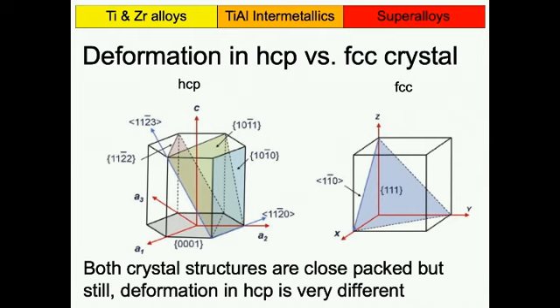This is a relatively close packed plane, but the basal plane as well. So both of those planes can act as a slip plane. And then on top of that, you even have one going here diagonal, but that is much more difficult to activate because it's actually not that close packed, and the arrangement of the atoms in there is not particularly flat. It's a bit wavy. But you have all these different planes. Okay? But the direction of the slip in those planes is actually not very different.